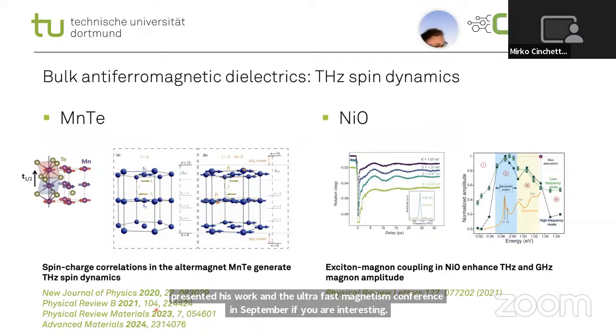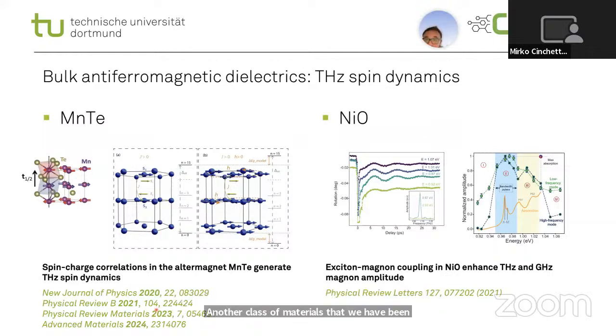Another class of materials that we have been intensively studying are bulk antiferromagnetic dielectrics. And antiferromagnets, you probably all know, have attracted a lot of attention recently because they exhibit spin dynamics in the terahertz range, which could also be useful for applications. In this category, we have studied manganese telluride, which is a charge transfer insulator, and recently has also been shown to be an altermagnet. And here, our main idea was to exploit the spin charge correlations in this material to optically generate terahertz spin dynamics.